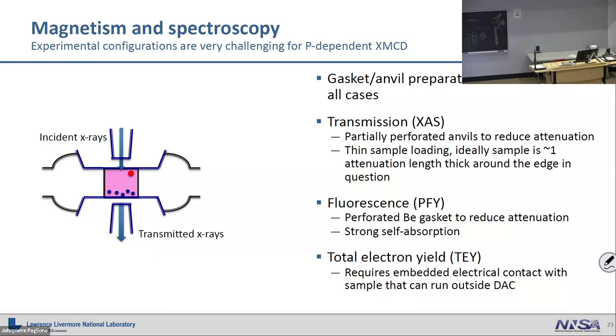The other challenge is you want about one attenuation length or so of thickness of your sample, and so that tends to be like 2 microns or 3 microns or something like that. So I very deliberately showed a couple of little powders that are sitting on the diamond here as opposed to them being piled everywhere. You can easily make this DAC, get your x-rays aligned and everything, put it in there and find that you made a beam stop at the energy and you get nothing out of it. You've spent all this time making a DAC and you've got to take it apart and do it all over again. And these diamonds tend to break a lot easier because these are called partially perforated.